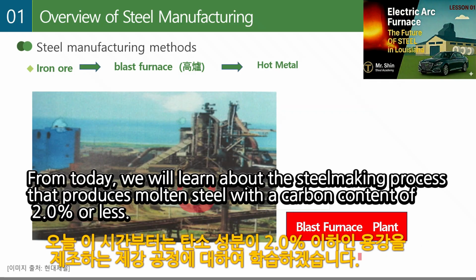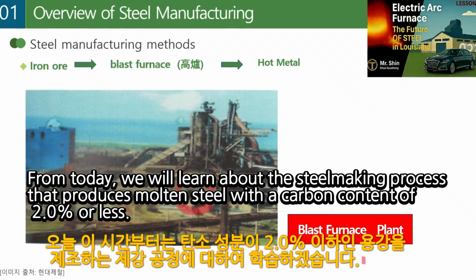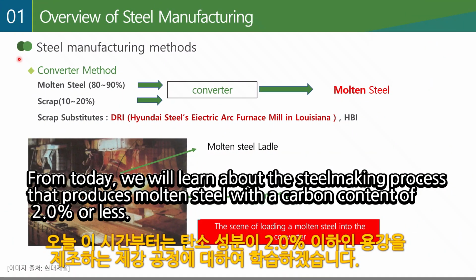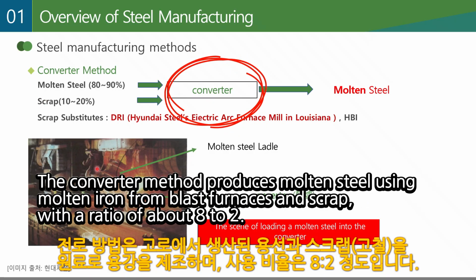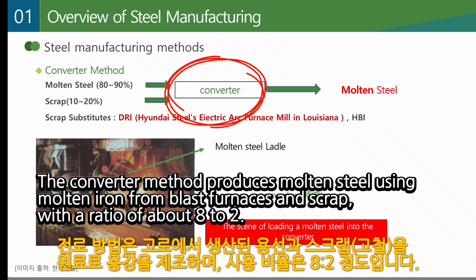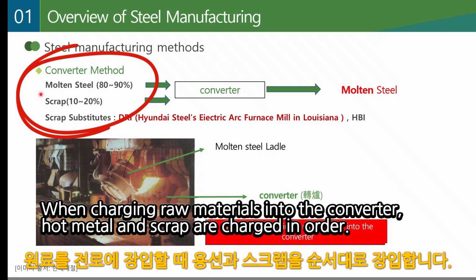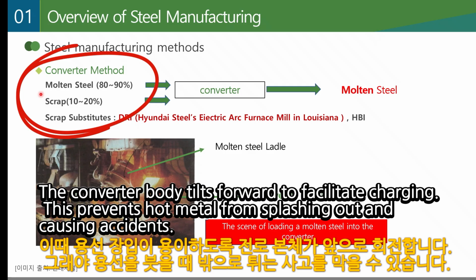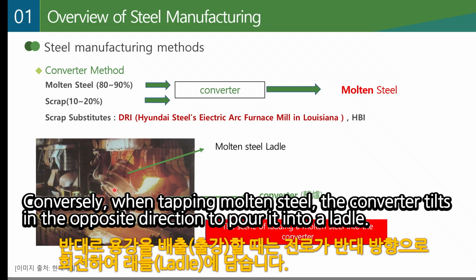From today, we will learn about the steel-making process that produces molten steel with a carbon content of 2% or less. The converter method produces molten steel using molten iron from blast furnaces and scrap with a ratio of about 8 to 2. When charging raw materials into the converter, hot metal and scrap are charged in order. The converter body tilts forward to facilitate charging. This prevents hot metal from splashing out and causing accidents.